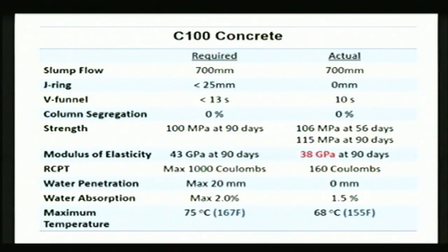So what we did, we actually put some limits on ourselves. We said, all right, this is 100 MPa concrete. This is the one that's going into the core walls. And the 100 MPa concrete should have a slump flow of 700 millimeter, which is quite high. J-ring less than 25 millimeter. J-ring is the difference between the slump flows, one without the actual cage, and one after the cage, and the difference should be less than 25 millimeter.